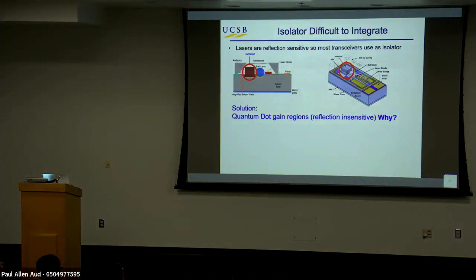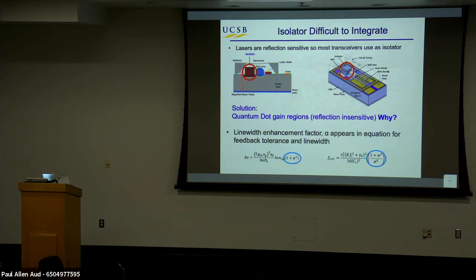Okay, so let's talk about quantum dots to remove the isolator. So we want to get rid of this bulk isolator. It's fairly expensive, obviously fairly big. Why are quantum dot lasers better? Why are they less reflection sensitive? Well, the critical field for instability in a laser, whether it's coherence collapse or other instabilities, goes like the linewidth enhancement factor to the 4th power.